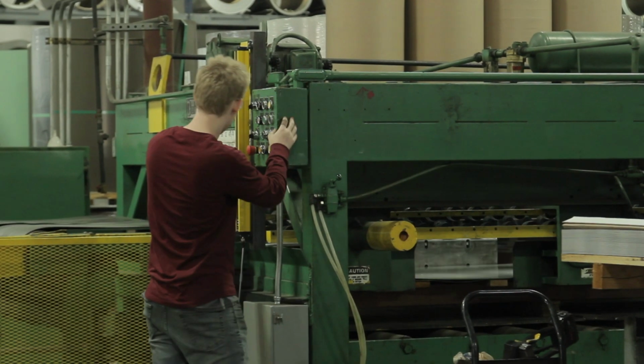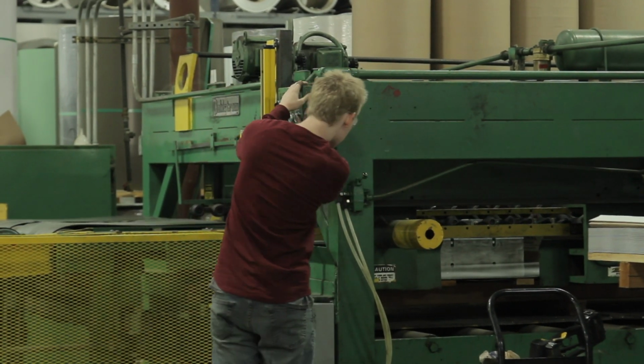And as you know, sometimes these panels are getting hit with a 600 ton press, and that could be a small dust particle, a small cardboard particle that could really indent that steel or that painted metal, and then you have a defect. So getting that panel as clean and dry as possible is so important. And again, free from any lubricants, so there's not any kind of reaction with the lubricant and the adhesive system.